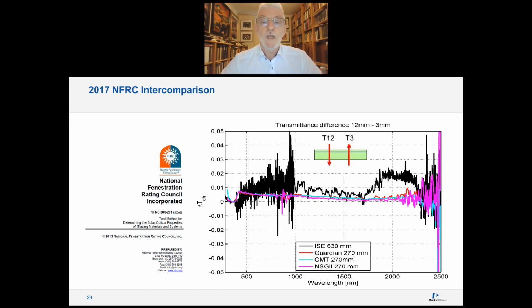And what you see here is the difference in transmittance measurement if you go in 2 directions in the glass. And this is an extreme glass because it's a 12 millimeter and a 3 millimeter, which is laminated. And the PVB foil is diffuse. So there's a diffuser in between, and it's closer to the surface on the 3 millimeter side than on the 12 millimeter side. So that has a special effect in the measurement. And normally you should get about 0.5%, roughly or less, transmittance difference in the 2 directions. And that's what we actually got.